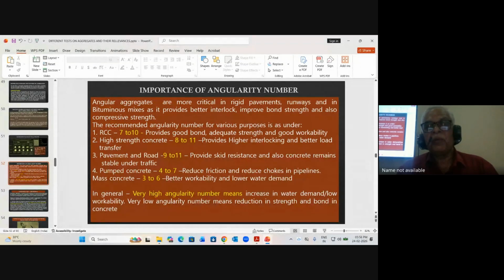Recommended angularity number for RCC is 7 to 10, for a good bond, adequate strength and good workability. High strength concrete 8 to 11 provides higher interlocking and better load transfer. 9 to 11 for skid resistance, which is best for skid resistance and keeping concrete stable under traffic. Pumped concrete 4 to 7, mass concrete 3 to 6. These are the recommended angularity numbers. Again, it's not given in the standards, but it's a general norm based on many literatures.